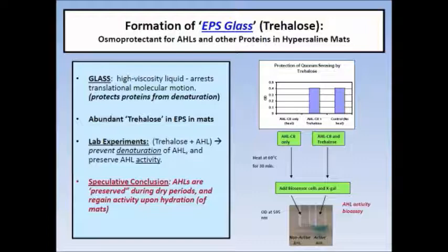And so when we create EPS glasses in the laboratory, we can expose the signals to high temperatures, to very alkaline pHs even, and they're able to survive and retain their biological activity. So that's very interesting to us because in nature, bacteria are exposed to this desiccation process in many, many places, and it allows them to kind of just quickly begin metabolizing once they're rehydrated again.